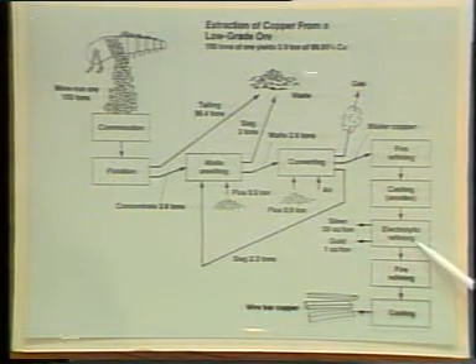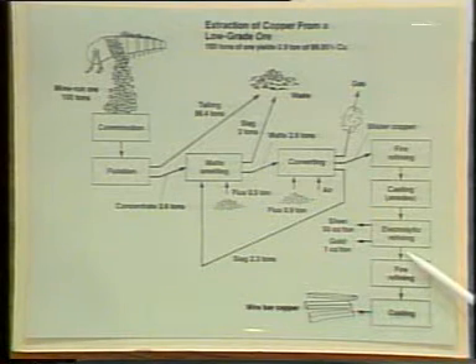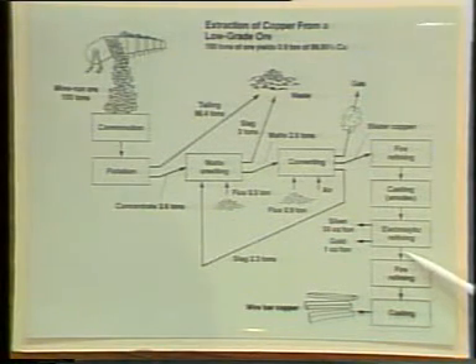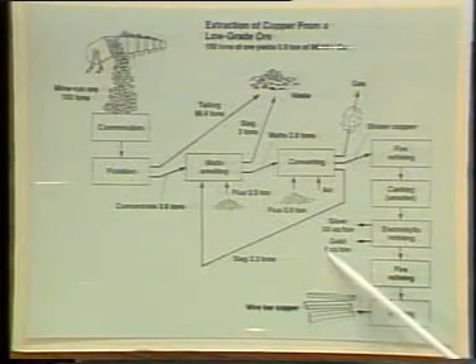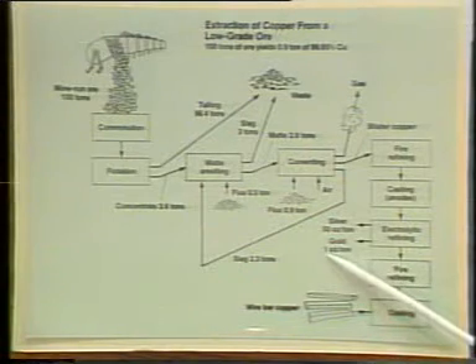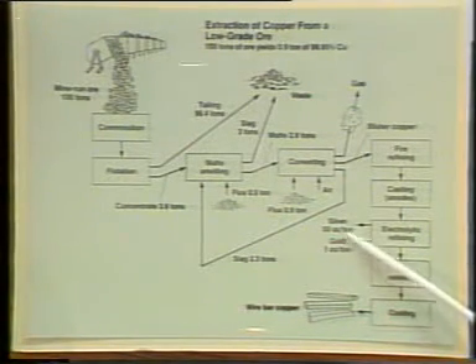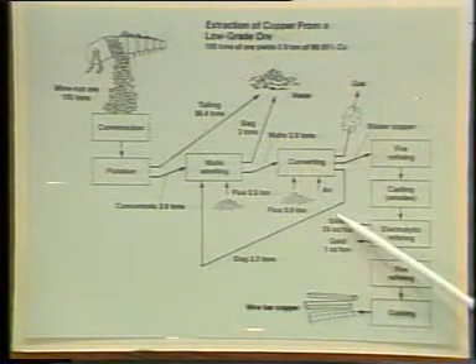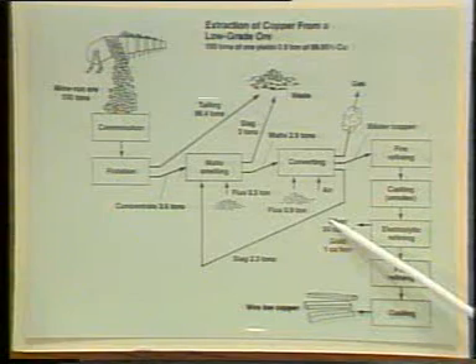cathode, now pure copper. And in the process, we will drop out all of the noble metals, and the selenium and the tellurium. And so we get gold and silver and platinum, palladium, rhodium, iridium, selenium, and tellurium.